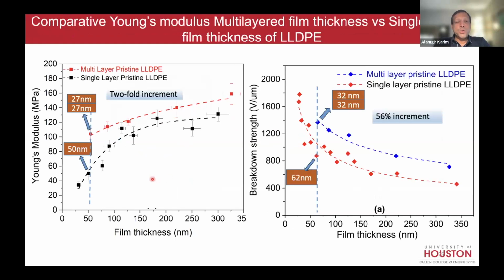If this is really true, what I'm saying, I put my student to the test and said, look, a single 50 nanometer film should have a lower energy breakdown strength, and thereby energy storage, compared to two stacked films that add up to that same thickness. Indeed, it's true. So you can see that the modulus also plays that same game. As I said, but it's not really connected.